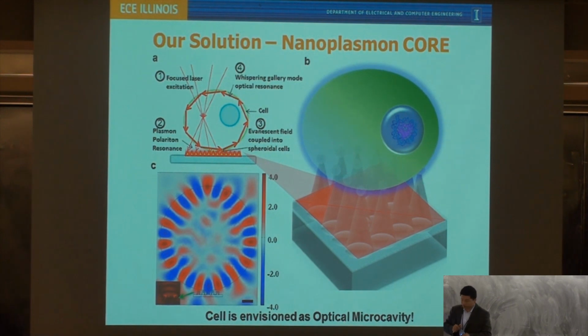In this case, if we use spheroidal cells and let them sit on top of a nanoplasmonic substrate, we're thinking, can we couple the plasmon wave into the whispering gallery mode inside the cell cavity? If we envision the cell as a perfect spheroidal or spherical microcavity, can we excite this whispering gallery resonance mode inside the cells? If we can do that, then we can confine the light field within the cell to improve the equivalent light intensity inside the cell to excite the molecules, especially in the cell membrane, with a much higher intensity. So that's our basic idea.